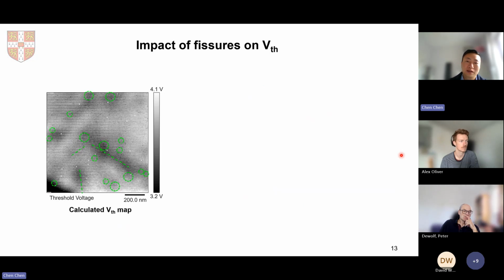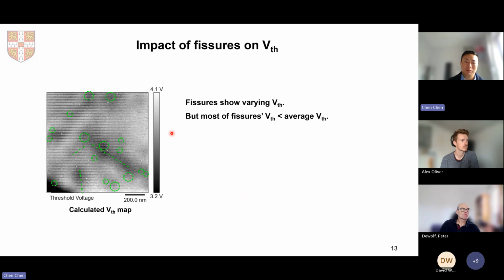First, let's check the impact of fissures on local threshold voltage. As you can see, for these highlighted fissure regions, their contrast is not consistent, which suggests fissures show varying threshold voltage. Also, for most fissures, they show a darker contrast, which suggests most fissures' threshold voltage is smaller than the average threshold voltage of the whole area. For example, for this local fissure, its local threshold voltage value is 3.44 volts, smaller than the average threshold voltage of 3.7 volts.